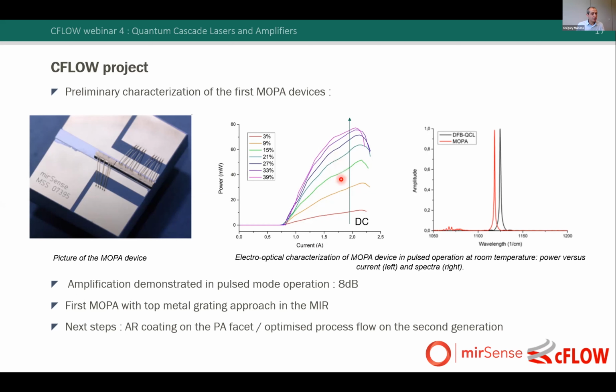So as mentioned, this structure was not optimized for the continuous wave emission. But we wanted to demonstrate that we were able to amplify the signal coming from the DFB section. And we compared this optical power obtained on this device with the typical optical power we had on the same DFB lasers without the amplifier. And we have demonstrated that we are able to amplify this signal with an amplification of 8 dB.